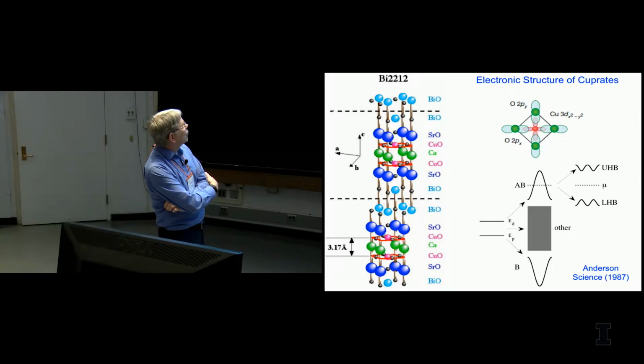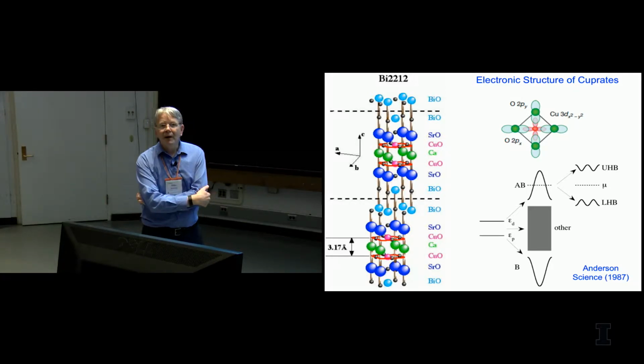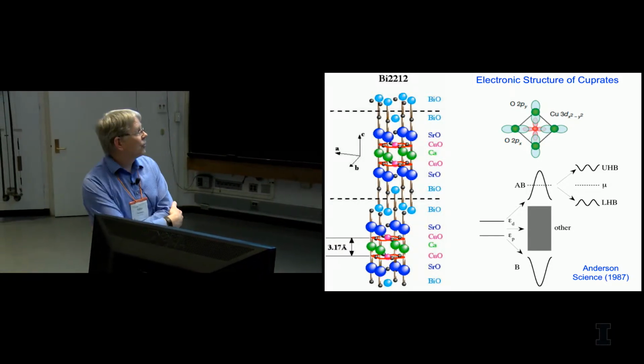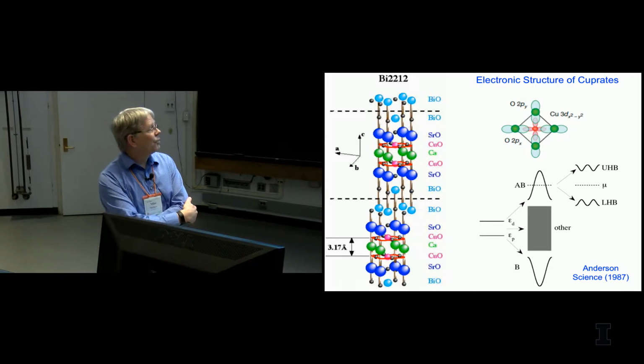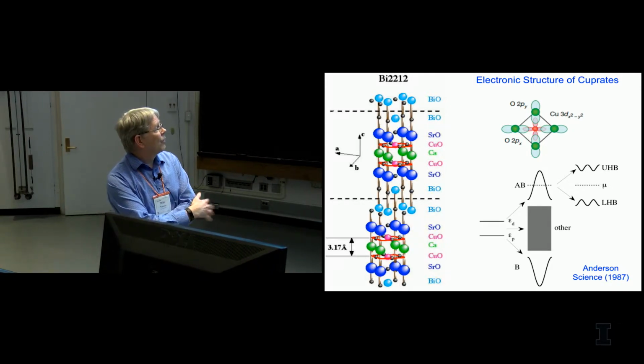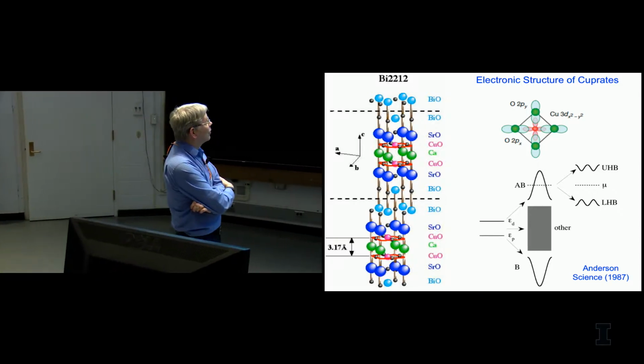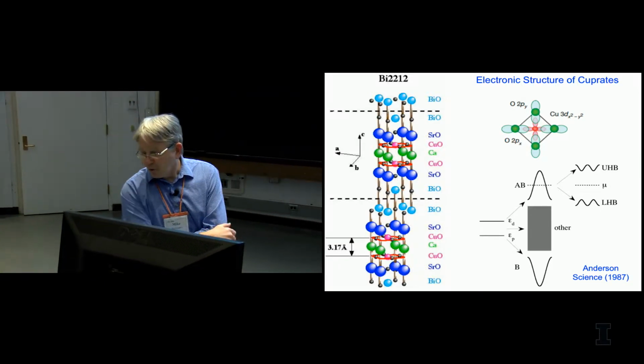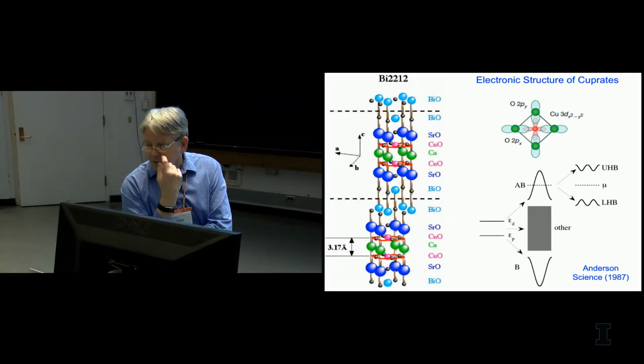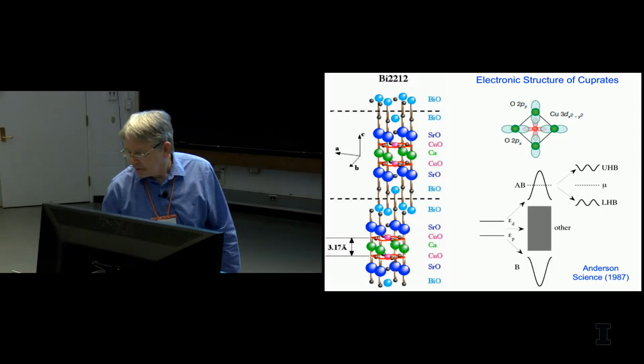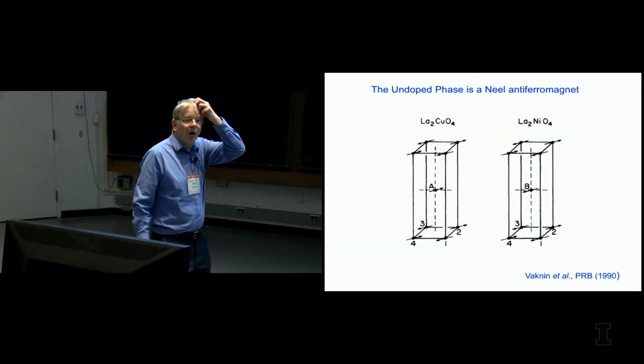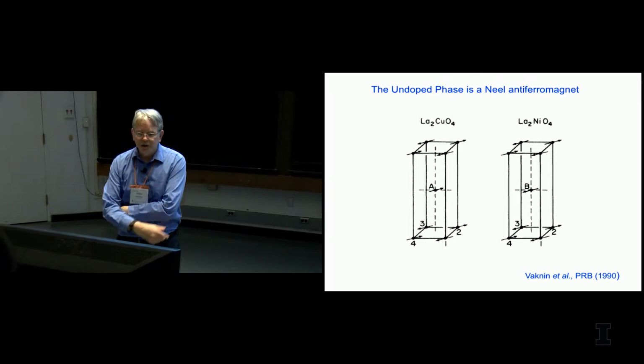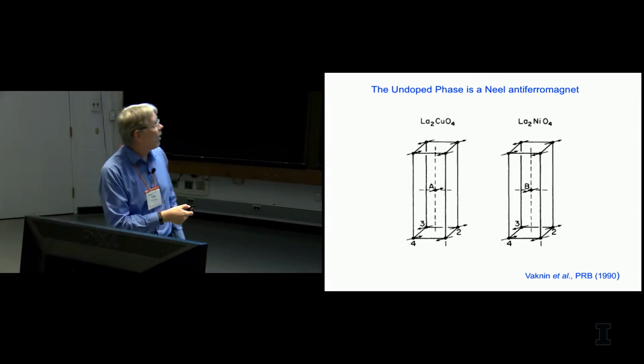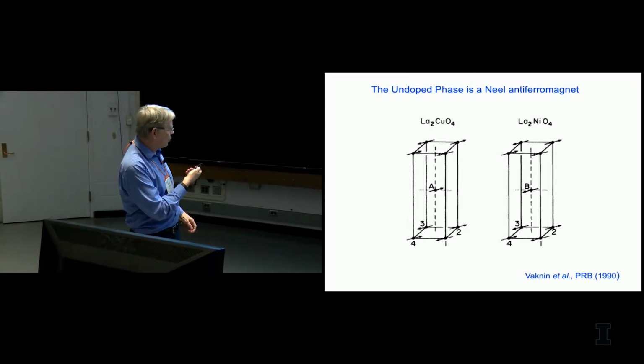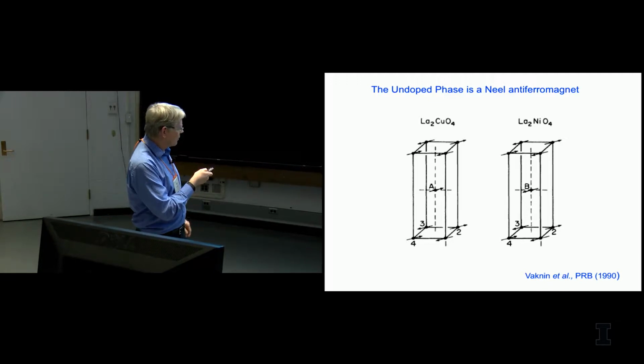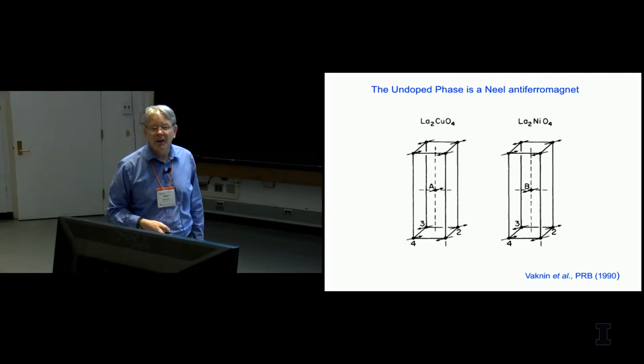And of course, Phil Anderson realized early on that you would have a half-filled band, and therefore, since the material he predicted was going to be an insulator, you expect that something like the Mott-Hubbard or the more modern variety, charge transfer insulator, would occur. Now, some of you might remember Phil also proposed that the stoichiometric material would be a quantum spin liquid. And of course, it turns out it's not. It's actually a garden variety antiferromagnet. And the antiferromagnetic ground state you see is actually not much different than what you see in other transition metal oxides. This compares lanthanum cuprate with lanthanum nickelate. And the magnetic structure is almost identical.